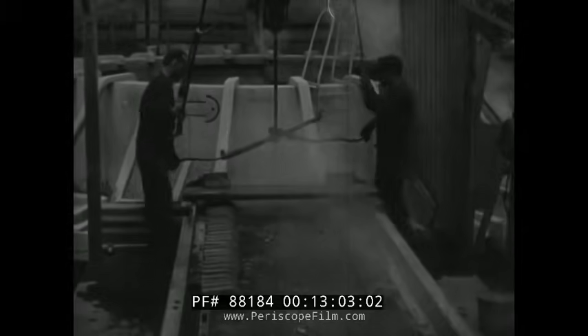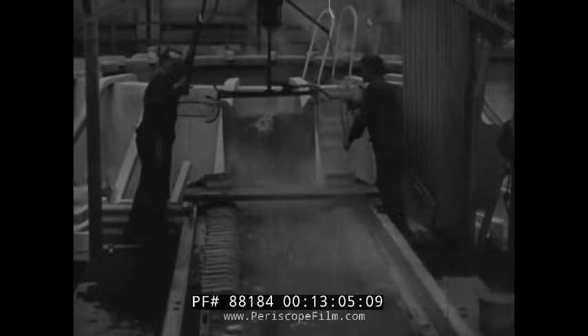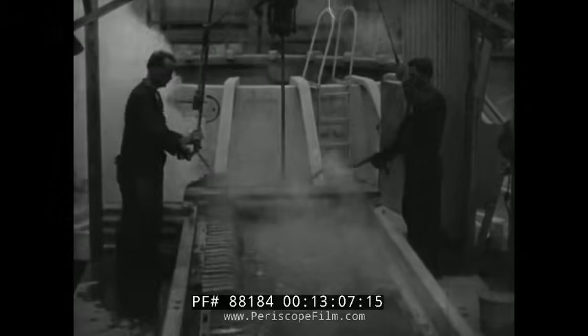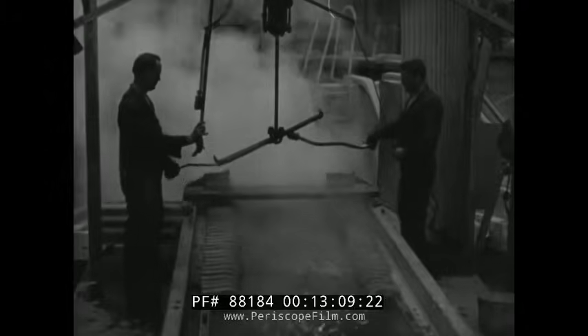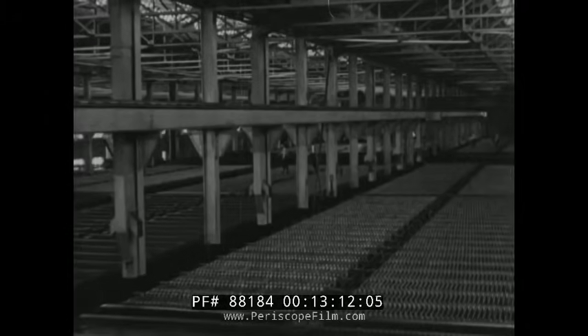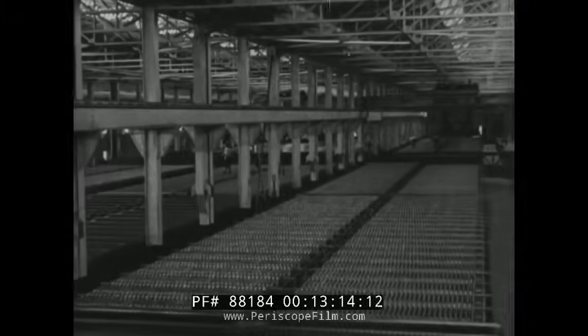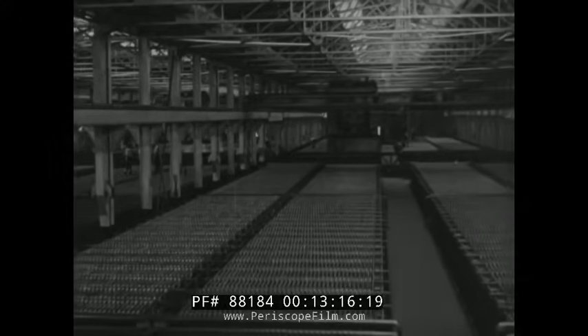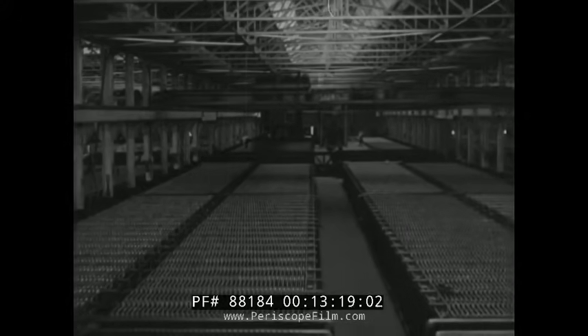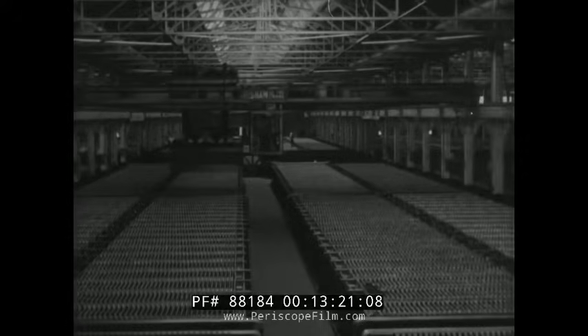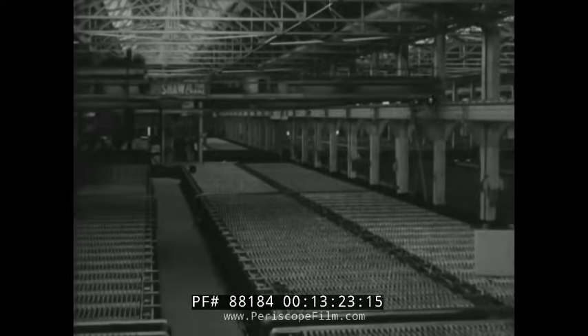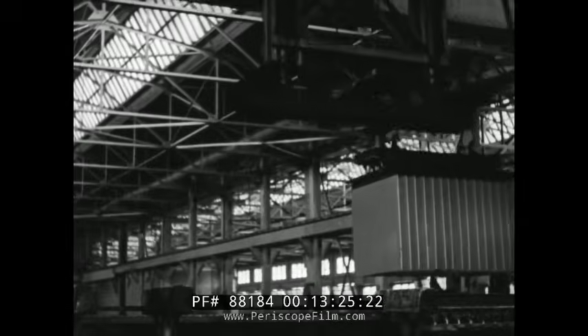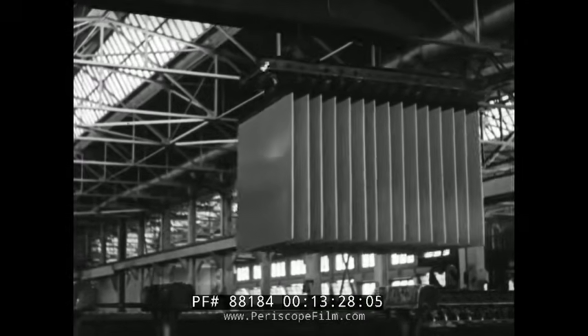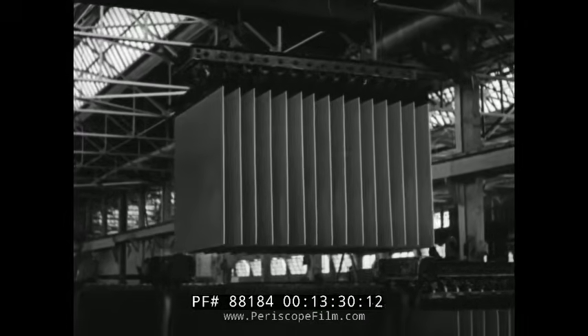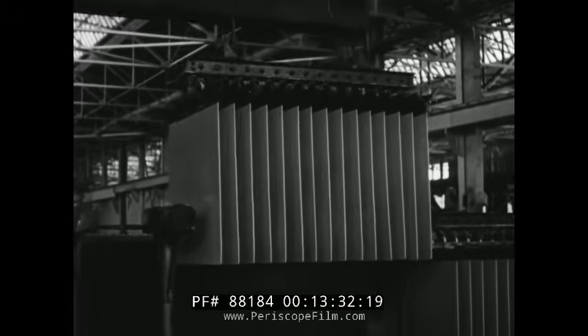Water sprays are used to chill the hot metal, after which the anode is removed from the mold and hung in a cooling tank. Later it is taken to the electrolytic refinery. The tank house of the electrolytic refinery covers nearly 4 acres. It takes about 14 days for a cathode to grow to market size so it can be cut to customer specifications. A large quantity of copper cathodes is resmelted in the refinery and cast into wire bar and other special forms.